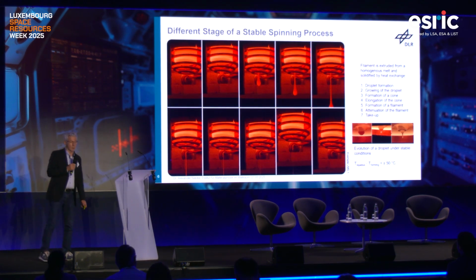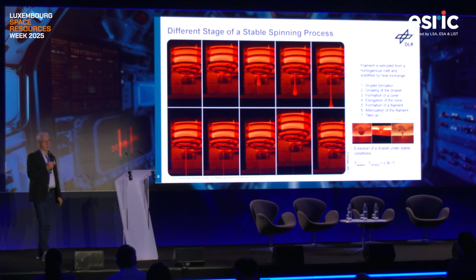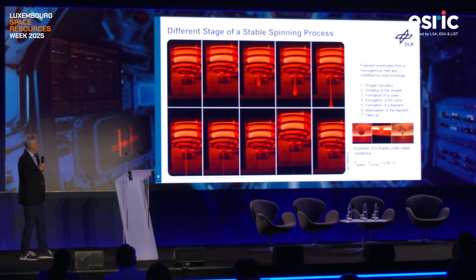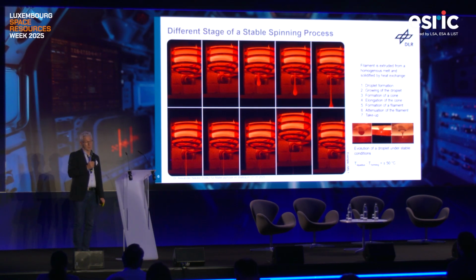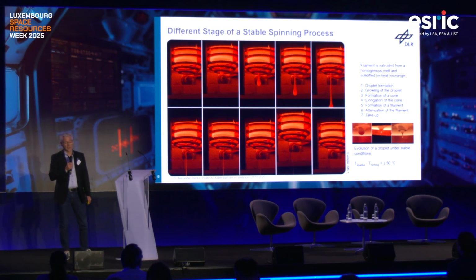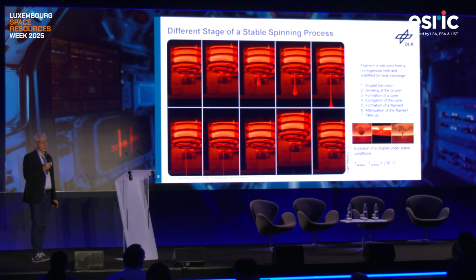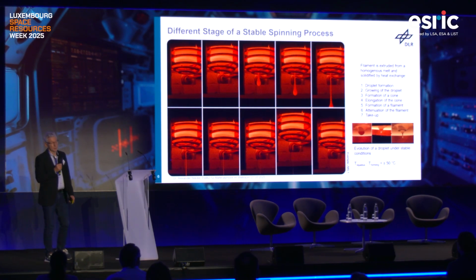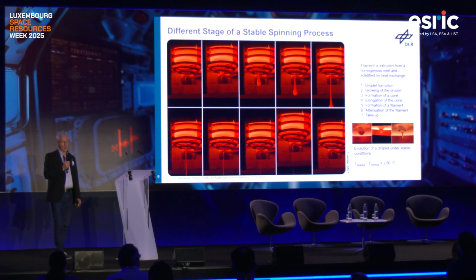So how does it work, this spinning process? You can see here on this slide the inductor and the crucible, which is a one-hole bushing, and there is a sequence of images that show how this extrusion works. First, we have the formation of a droplet at the outlet of the nozzle. In the second step, this droplet is growing until it gets a critical mass and falls down in the direction of the winder. At the same time, the glass jet that is coming from the nozzle is elongated, and continuously a small fiber is formed.